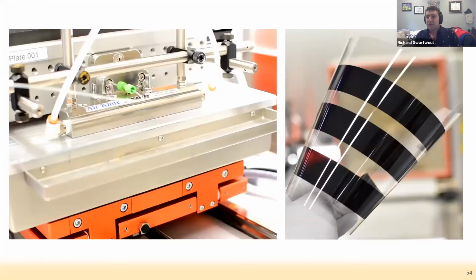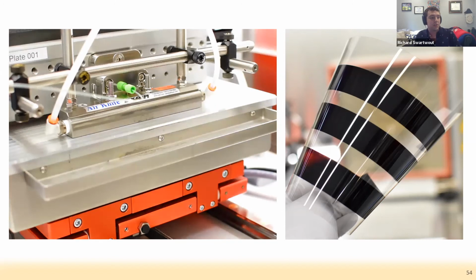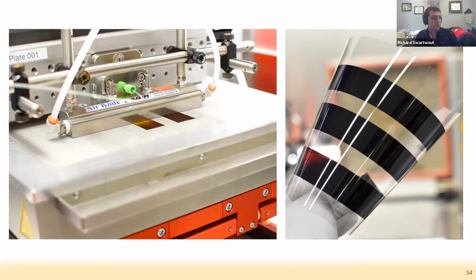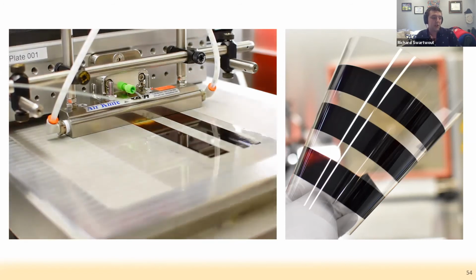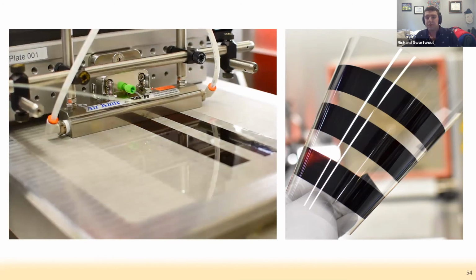With the active drying, you can expand your width of your stripe. The last one was half an inch, 13 millimeters, to 25 millimeters. You can also run much faster, so this is 3 meters a minute, but you get much more uniform drying, much more uniform films. And this is how we print perovskites here today.